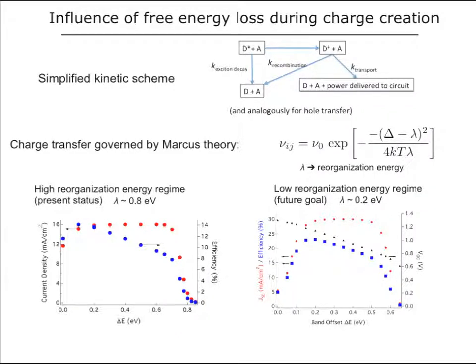Right? This is a critical component in the charge transfer and how to dissociate the exciton. So what we can do is calculate efficiencies based on, first of all, delta G. I have written here delta E, but it's really delta G, the band offset. And putting in a conventional value of the reorganization energy of 0.8 electron volts, with that value, we can fit the current data, like the 7% device I showed you. We can fit it pretty well.